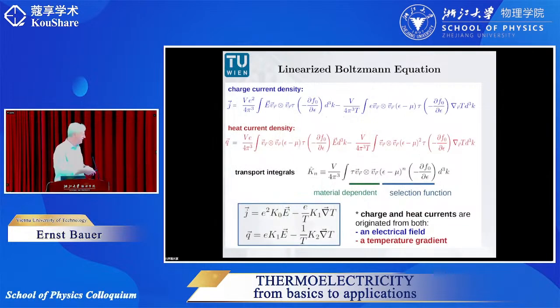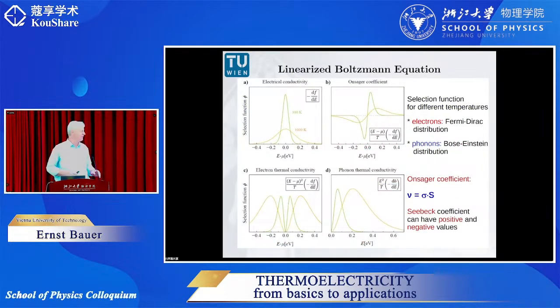So we have seen that we have transport integrals K1, K2, and K0 as well. That means 1, 0, and 2 are important for this exponent n, and the so-called selection function. The simplest one is the electrical conductivity, because as we have already seen, n is 0, and therefore the selection function consists just of the energy derivative of the Fermi-Dirac distribution function.